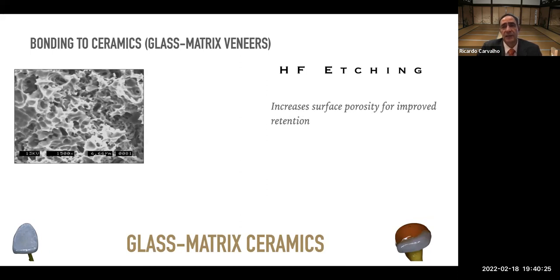What hydrofluoric acid etching does, it removes the silica from the surface and increases the surface porosity, which will then help in promoting micromechanical retention to these veneers. It also promotes a chemical change on the surface that raises the surface energy. And we all know that by increasing the surface energy, you facilitate the spreading of any other components that you're going to place in there. In our case, the silane.